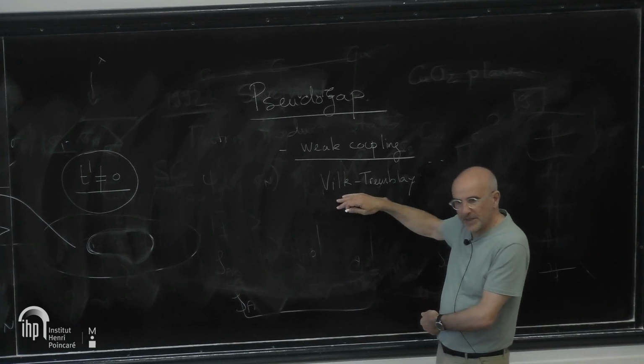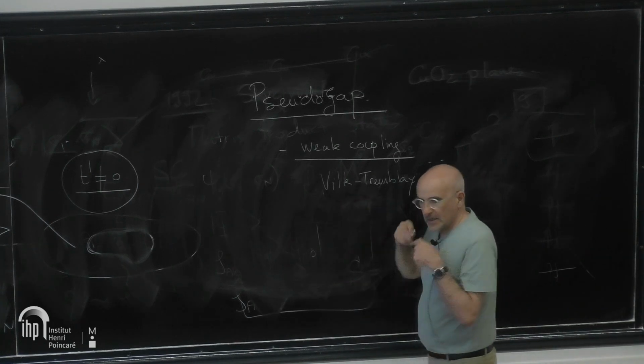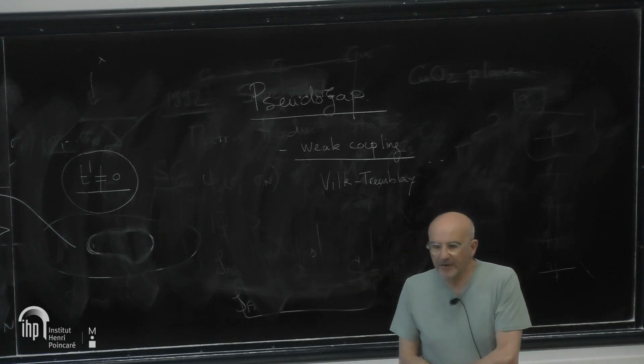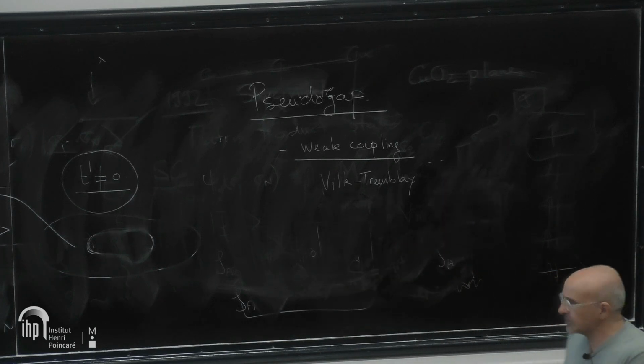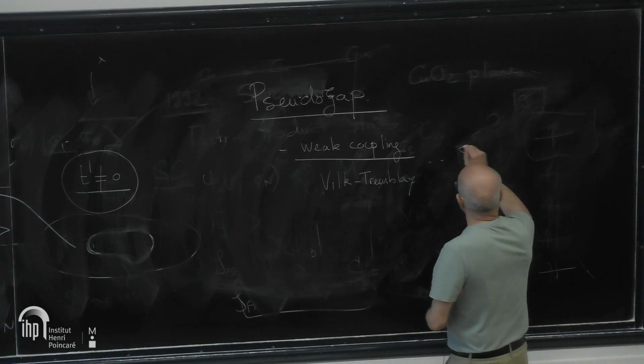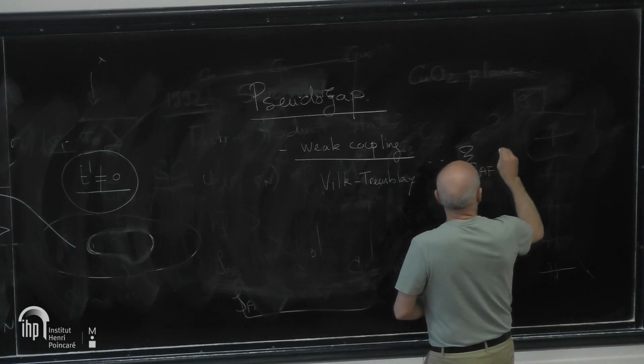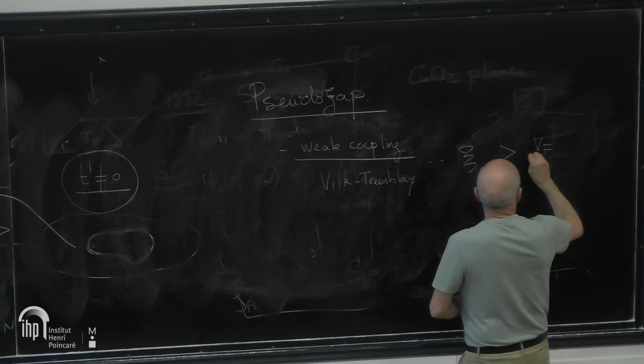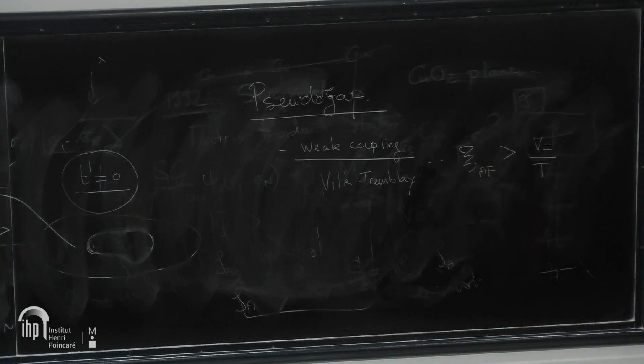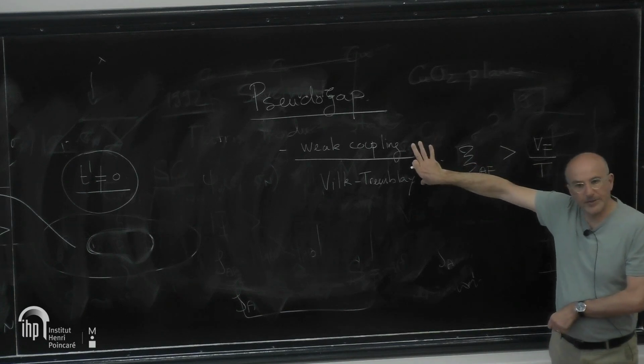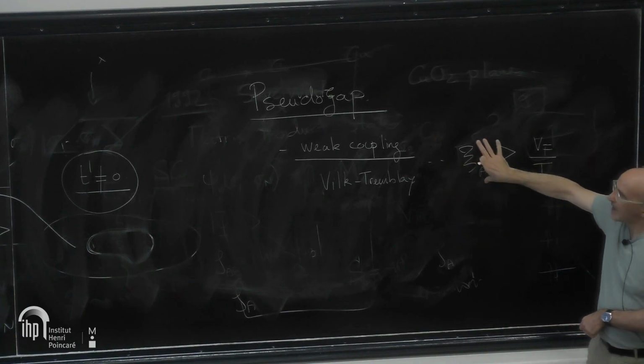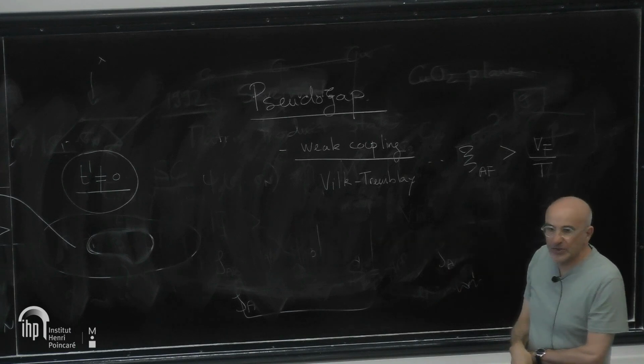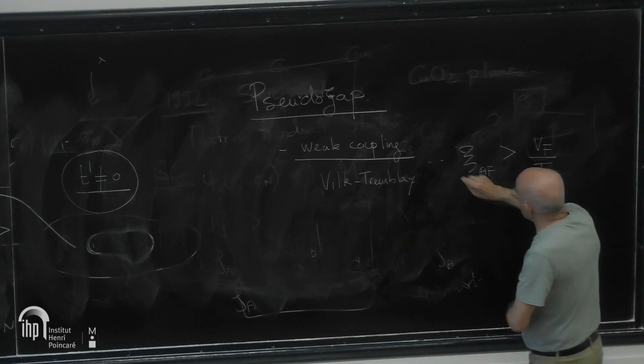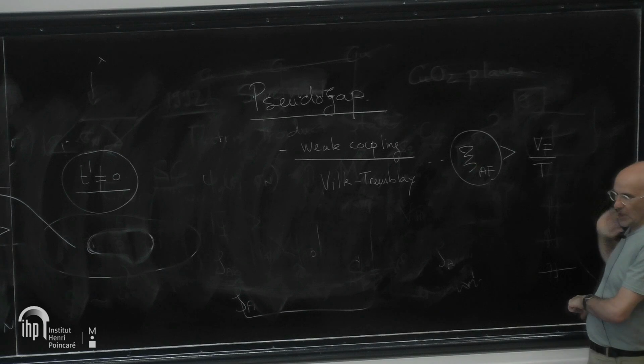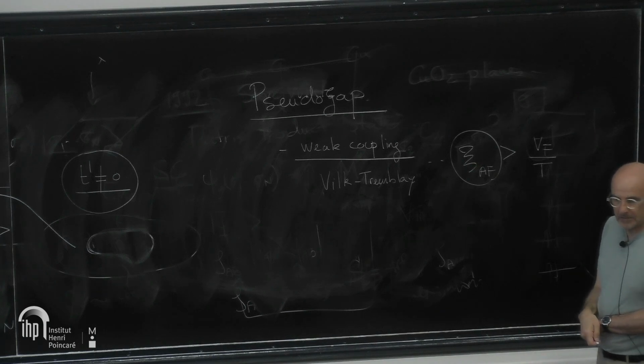This Vilk and Tremblay theory is telling you that long-range antiferromagnetic fluctuations in 2D can create a pseudogap, provided that the correlation length for antiferromagnetic order is larger than the de Broglie wavelength. I can explain in the discussion session how this theory works. But this is a weak coupling theory, and the point is that in the regime where the pseudogap is actually observed, this antiferromagnetic correlation length does not satisfy this criterion. So we have a puzzle.